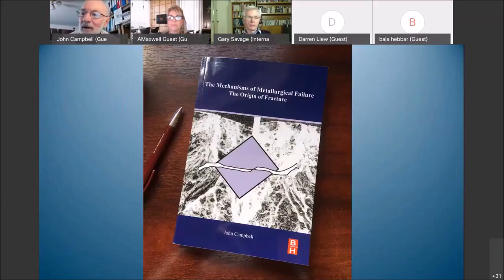But if we look back into some little known metallurgical history, which I report in my book, there were tensile tests of extremely slim whiskers of steel, which were so small that there was no chance they could contain a defect. And so when these were pulled, they went up to enormous stresses in the gigapascals. But when they finally fractured, they fractured by disappearing into a puff of smoke. There was no specimen left.